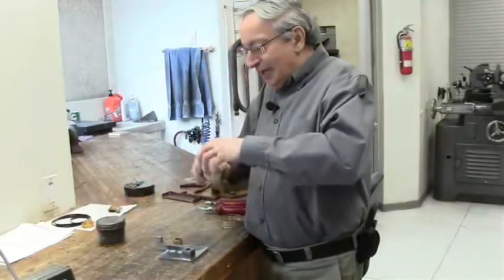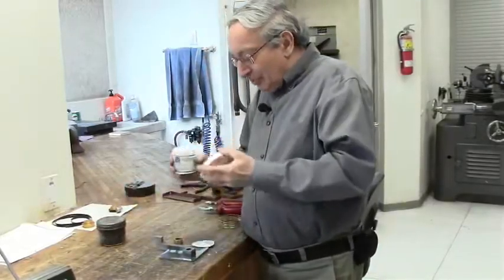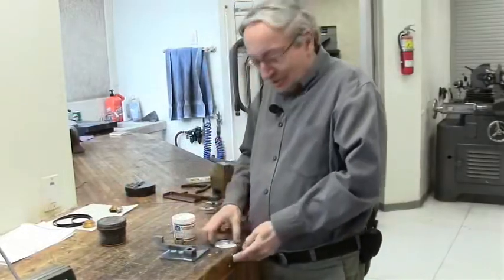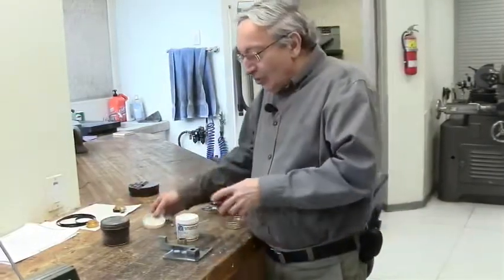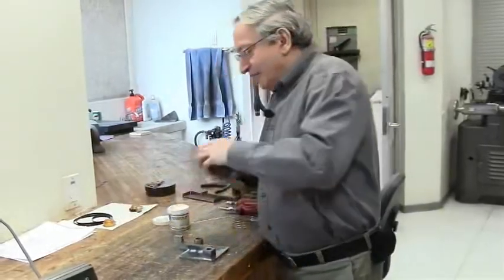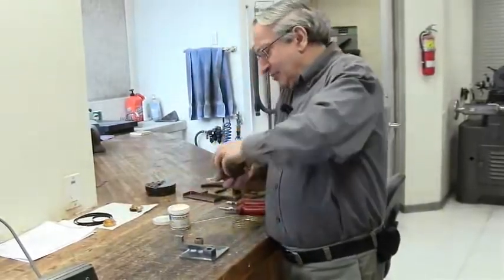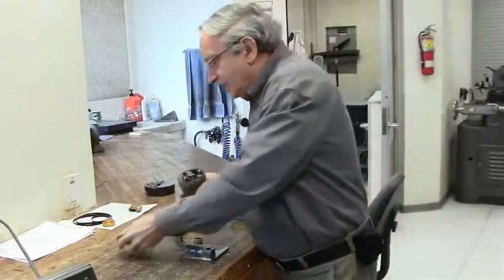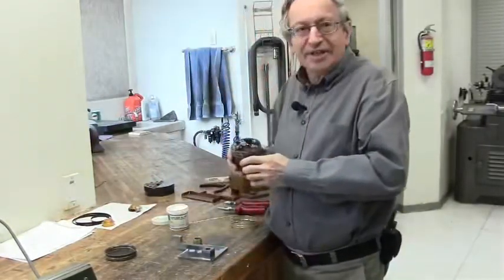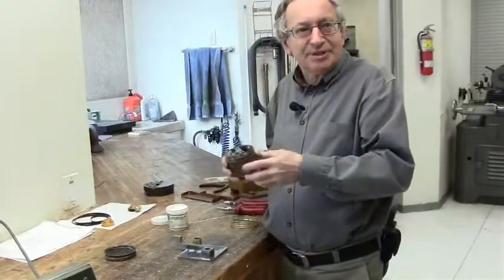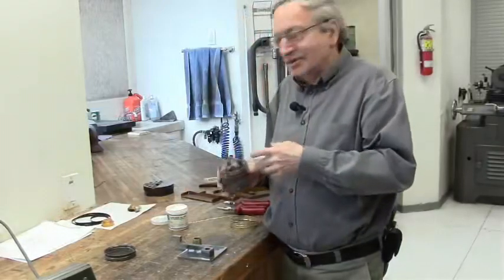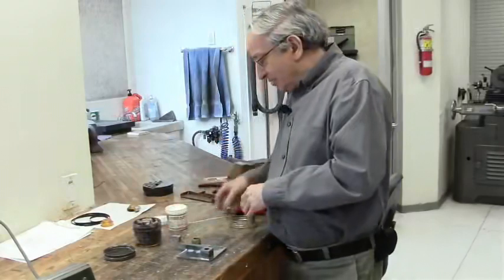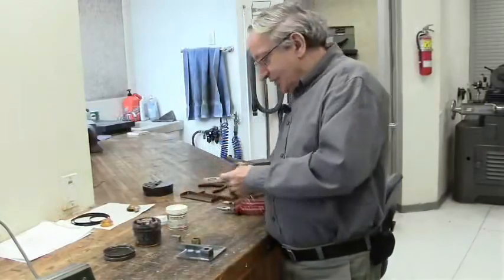Now typically there is a white flux, which is basically borax, which is the most common flux for all non-ferrous and can be used on iron as well. And there is a black flux, which actually, I'm not sure about the composition, I think it's some fluoride salt, which is used for stainless and harder to braze materials because it's more aggressive. Okay? The only expensive part here is a wire. The fluxes are cheap.